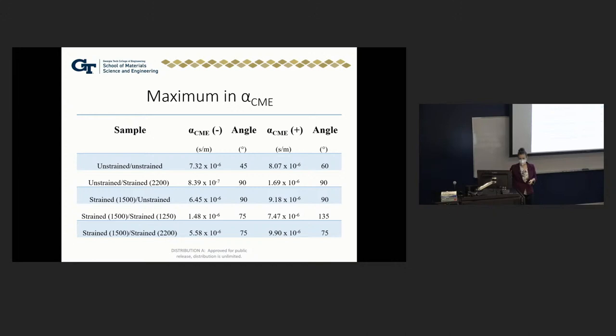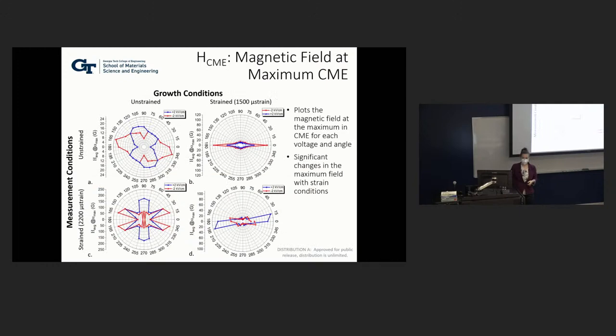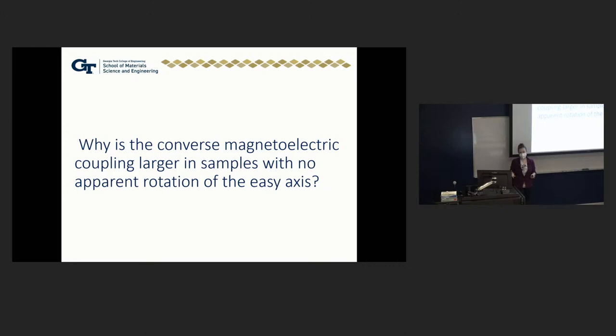I also want to highlight this really quickly here: this is the magnetic field that it took to get to the maximum in the CME. And you can see that there's actually a really significant change in these as well. This I thought was particularly interesting. So the question is, why is the converse magnetoelectric coupling larger in samples that do not show any apparent rotation in the easy axis? So to address this, we went back and looked at the MH loops themselves.